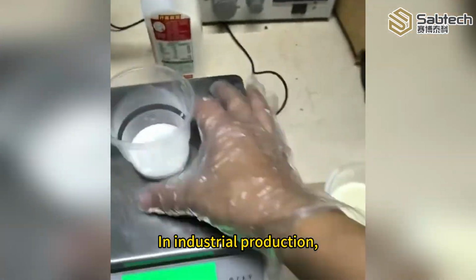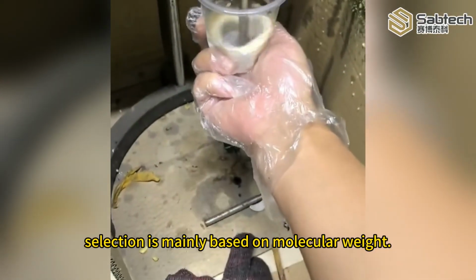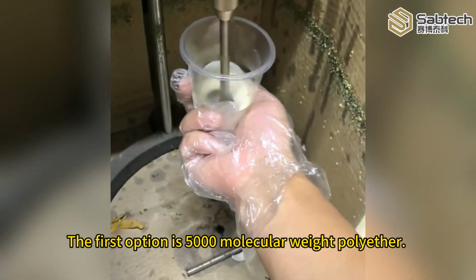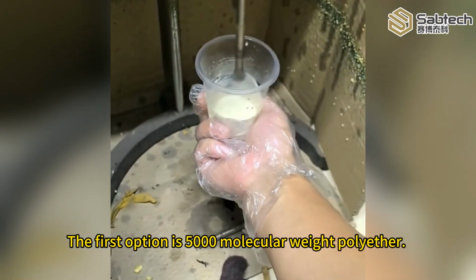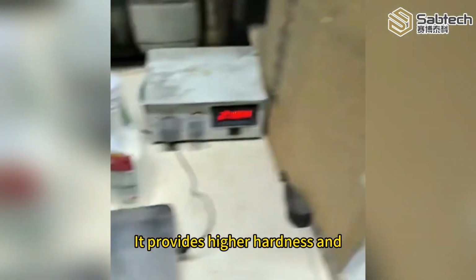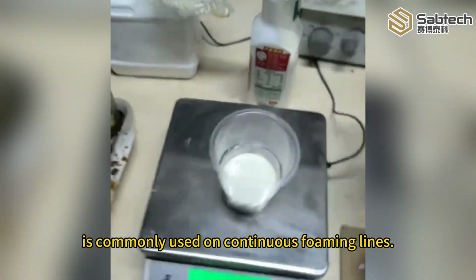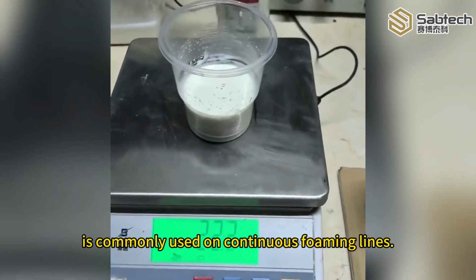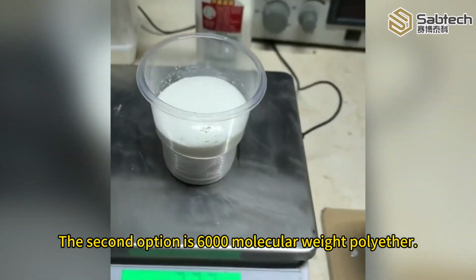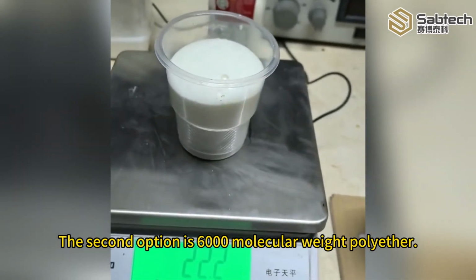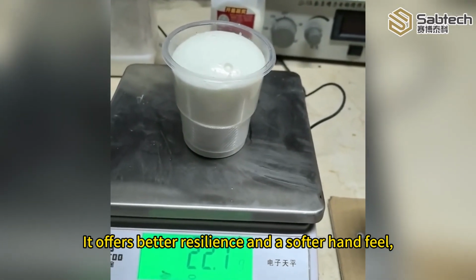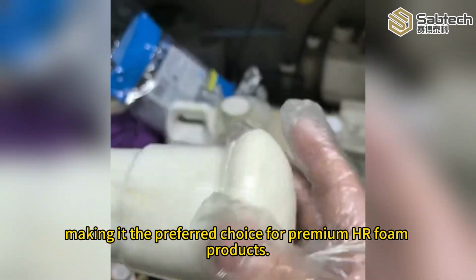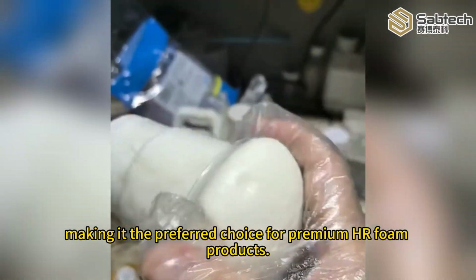In industrial production, selection is mainly based on molecular weight. The first option is 5000 molecular weight polyether. It provides higher hardness and is commonly used on continuous foaming lines. The second option is 6000 molecular weight polyether. It offers better resilience and a softer hand feel, making it the preferred choice for premium HR foam products.